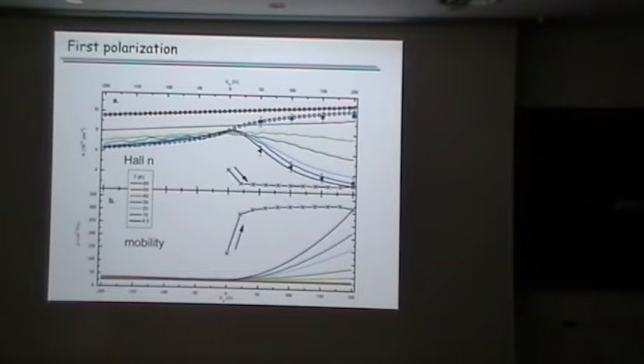And then you go back, and afterwards, this is completely reversible. This is not trivial. In most of the papers in the literature, people mention that you have irreversibility and stuff like that. You have to be very careful when you cool down and the way you proceed when you put the gate voltage. This is why the first numbers for the carrier density I gave you in our experiments are not reliable, because at this time we were not aware of that.